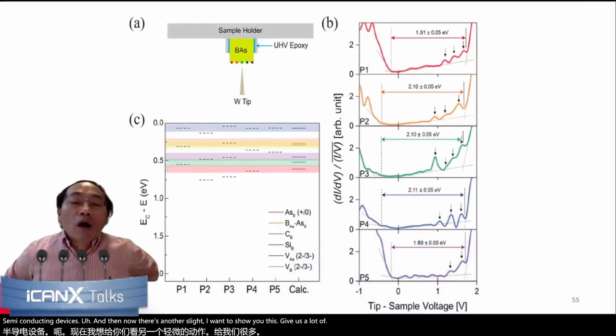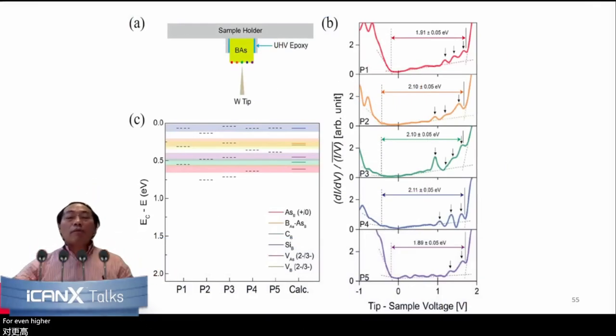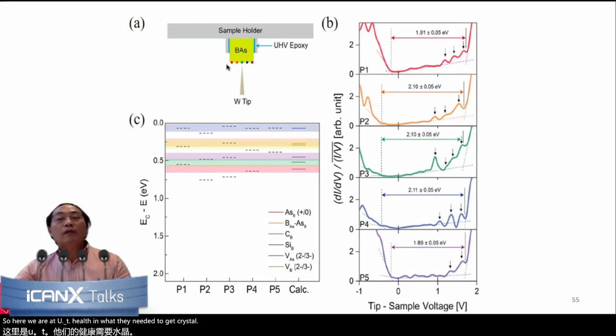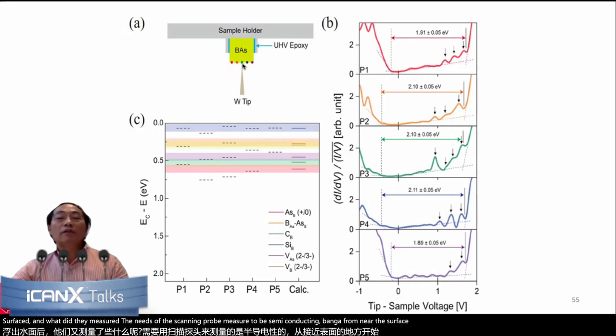And now there's another slide I want to show you. This gives us a lot more hope for even higher properties. So here, UT Austin took a crystal and added a broken surface. And this is a large surface as made, and this is the broken surface. And what they did, they used a scanning probe to measure the semiconducting band gap from near the surface to the inside and then to the outer surface.